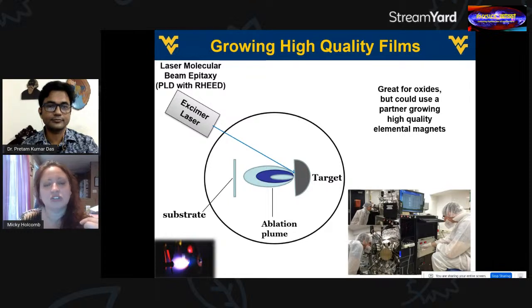Basically, you take an excimer laser, you shine it on your target that has the kinds of elements that you're wanting to deposit on your substrate. You have to spend some time creating the right environment, right? So your substrate has to be the right temperature. You have to have the right oxygen pressure in the system. You don't want to hit it too fast. So the speed with which the laser hits the target, the frequency, is relevant. There are actually a lot of finessing details to make it work right.